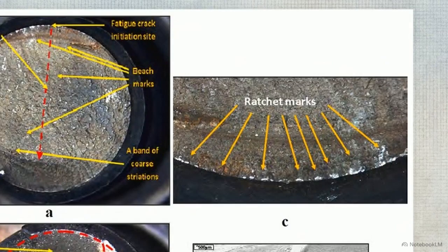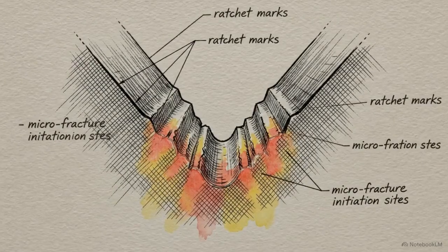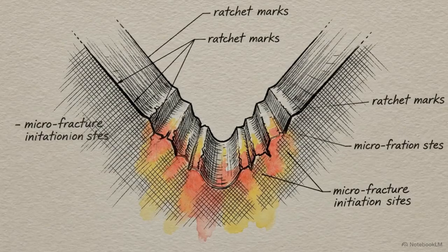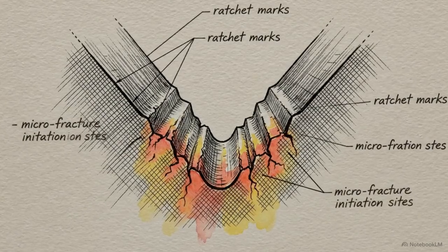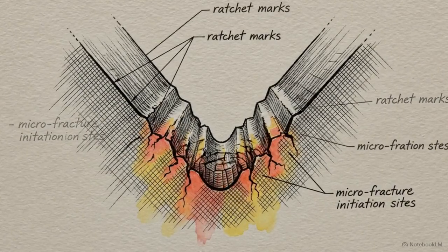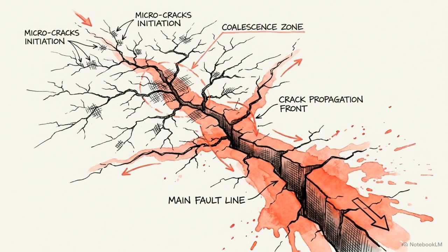Zooming in on the precise edge where the crack initiated, the yellow arrows highlight numerous microscopic ridges known as ratchet marks. Ratchet marks form when multiple stress fractures spark simultaneously along a harsh geometric boundary, in this case, the root of the thread. These individual cracks compete and propagate inward before coalescing into one massive crack front.